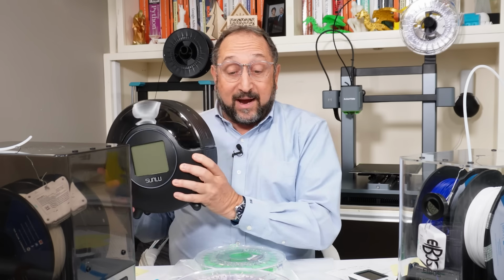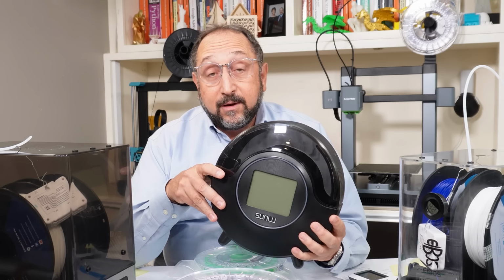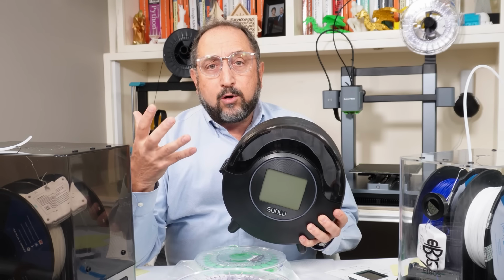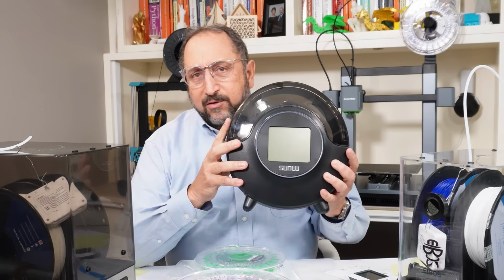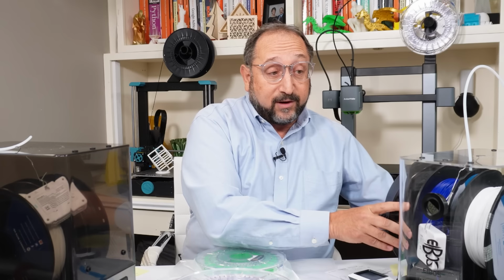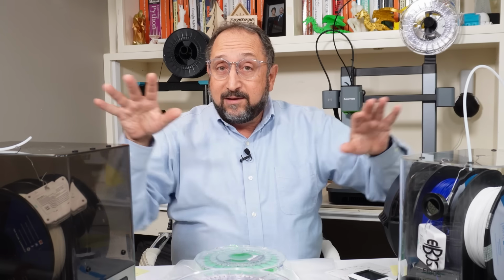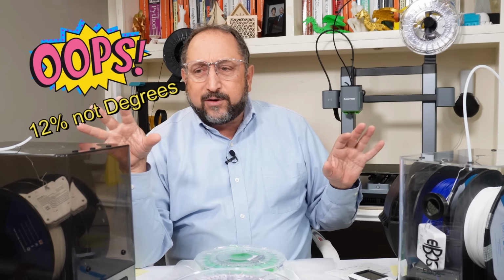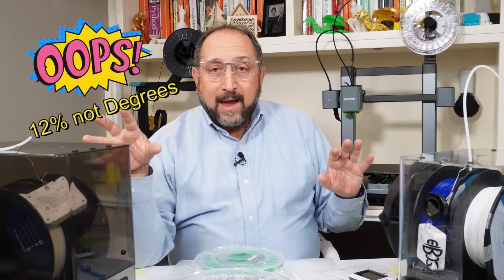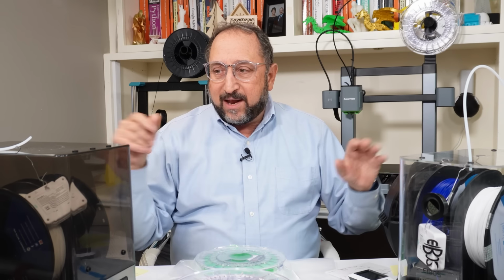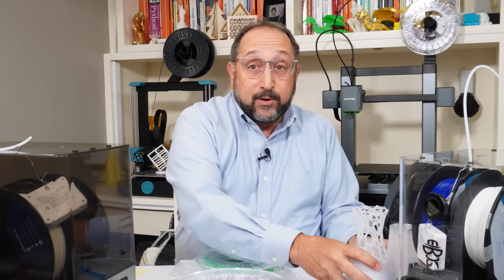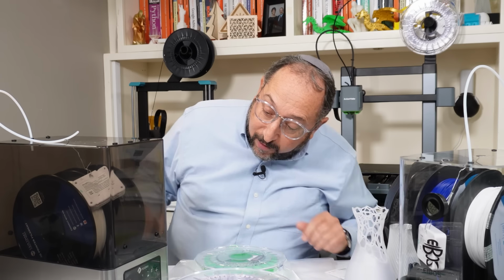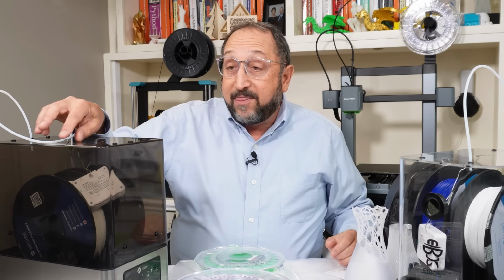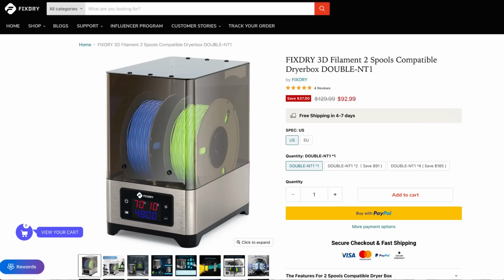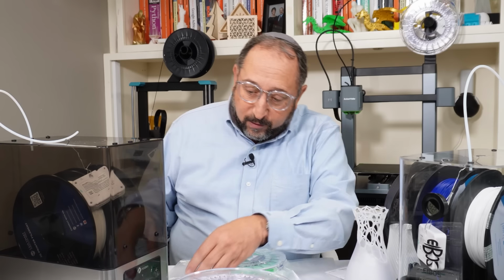Now, one of the things I did look at on these various devices is how low could it pull the humidity down. This one went down to about 15% relative humidity. These two larger models did go down to about 12% relative humidity or less, and so that is a slight advantage for them. This particular print dryer here is from Fixdry. It's a new model. They recently sent this to me in order that I can do these tests, so it was a free sample for the review.